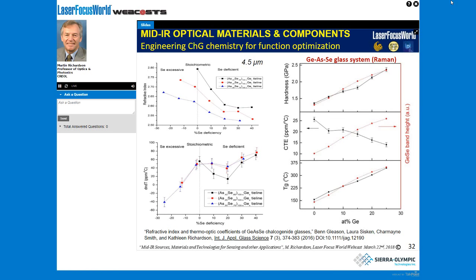And you see it here, a distinct two-sided region here, where on the left-hand side, on these two left figures here, we were basically in the region where there is a very strong correlation. This is a homogeneous type region here, where there's basically an excess of selenium, whereas on the right-hand side, the composition is selenium deficient, and we see more constant properties of the materials as a function of the